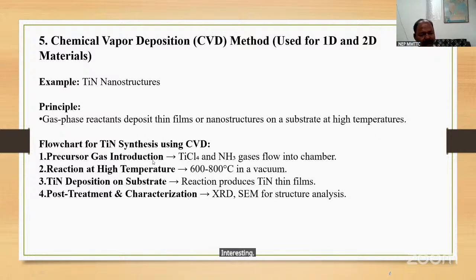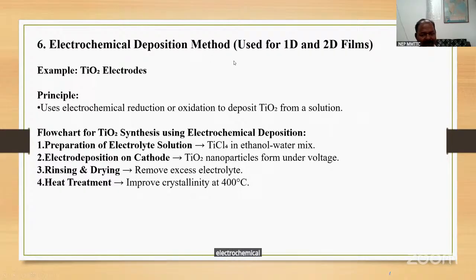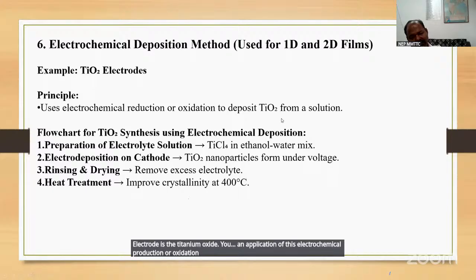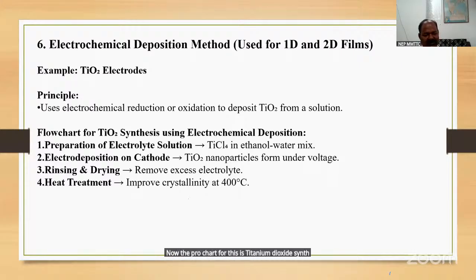Very interesting. And this is the flow chart. Electrochemical deposition method. This is also used for one and two dimensional materials. The electrode is titanium oxide. It is an application of electrochemical reduction or oxidation to deposit titanium oxide from a solution. Now the flow chart for titanium dioxide synthesis using electrochemical deposition: preparation of electrolyte solution, titanium tetrachloride in ethanol or water mix, electrodeposition on the cathode. So the titanium dioxide nanoparticles form